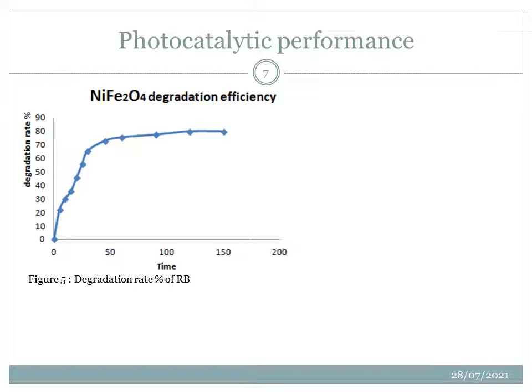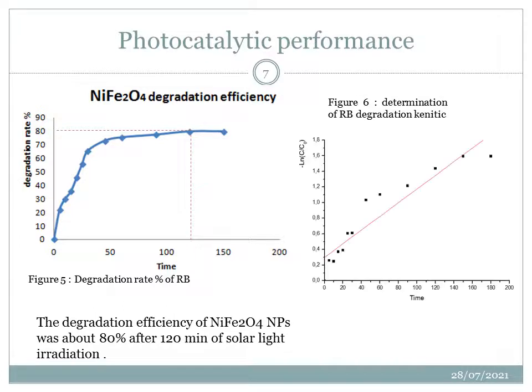Obtained results are shown in figure 5, where about 80% of rose Bengal was removed after 2 hours of sunlight exposure. For the degradation kinetics, as illustrated in figure 6, the linear fitting of minus ln C over C0 versus time for rose Bengal dye follows pseudo first order kinetic behavior, where K equals 0.1939 per minute.